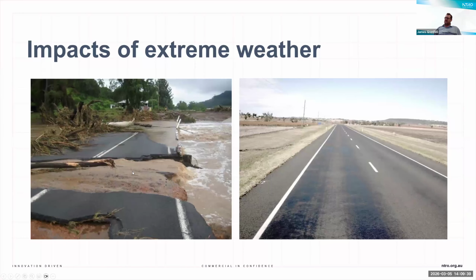So obviously dealing a lot with instances of very heavy rainfall, flooding events, but also Australia is a very hot country. We're subjected to extreme high temperatures, and again, that is particularly troubling for the sprayed seal network in terms of heating up binder, causing binder softening, flushing of binders, and reduction in the quality of the sprayed seal road network.